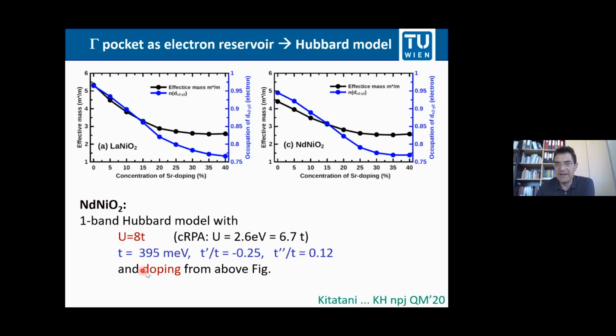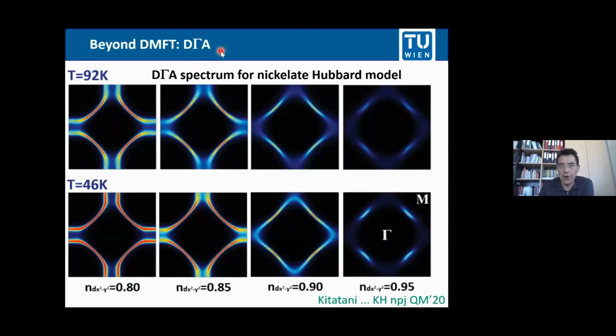So those are the parameters, and the doping you can read off from this figure, and then you can do calculations with one-band Hubbard models. And indeed, we did so. We now went beyond DMFT, only taking this x squared minus y squared orbital into account, and did the D-Gamma-A calculations. That is the Fermi surface at two different temperatures. And here you have the undoped parent compound, which has about 5% holes in the x squared minus y squared orbitals.